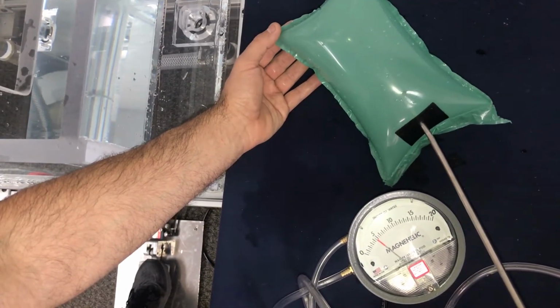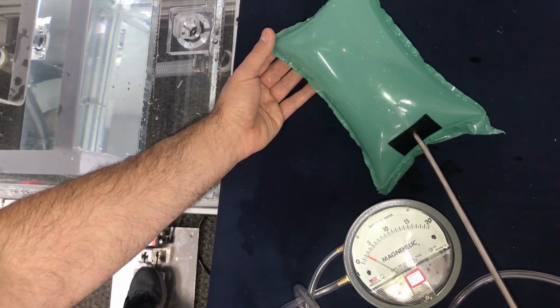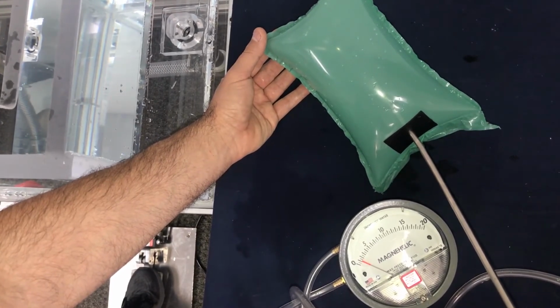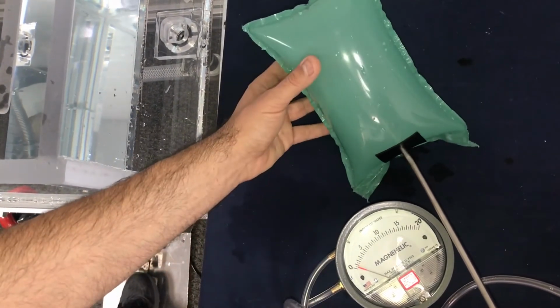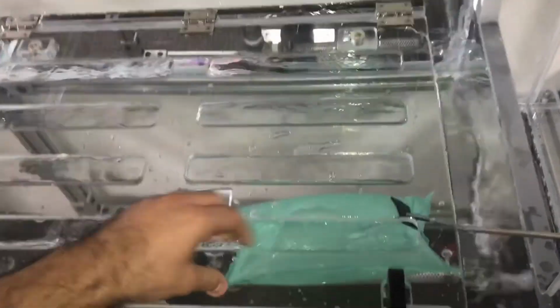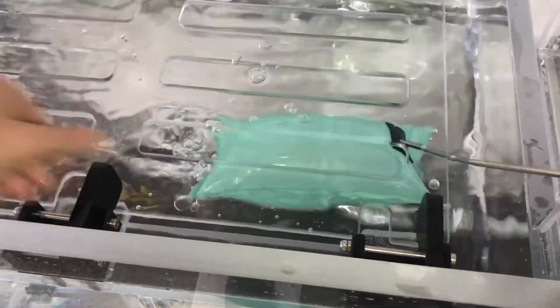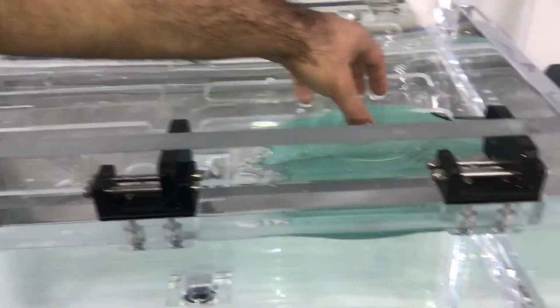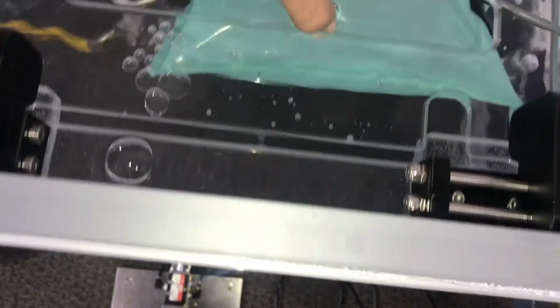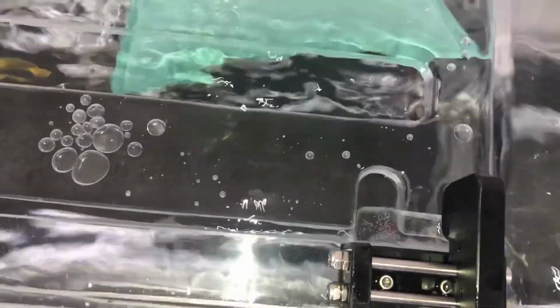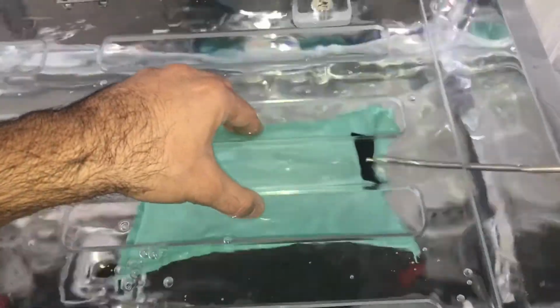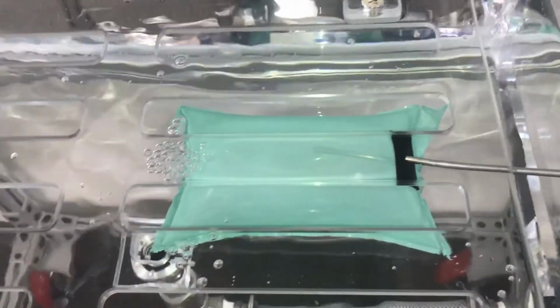That's because the pressure going in is not the same as the pressure being detected. Now, as your package is fully inflated, you will still see a little bit of pressure difference, and that's because you do have a leak. So in a way, you could theoretically detect a leak simply through a pressure difference in your test specimen. However, you will not be able to locate the leak. The leak location happens while the specimen is underwater.